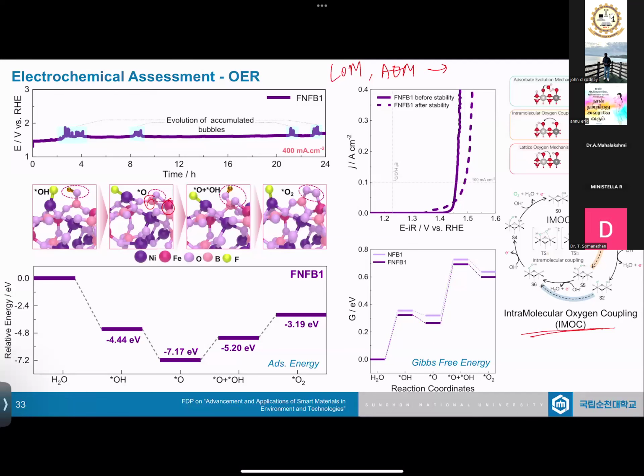Because we know very well, if you have an AEM process, you have water, then you have OH, then O, OOH, and O2, a four-step process, whereas for LOM, this step will not be there. Whereas in this one, the step became O plus OH, where two different radicals worked in our system, and which got us a very good activity. So when we don't ask the required questions, we will just report it by saying this is an LOM process or this is an AEM process, without clearly understanding that a different mechanism occurred inside the system. So it's very, very important to evaluate your material extensively and understand what's really happening inside the system.